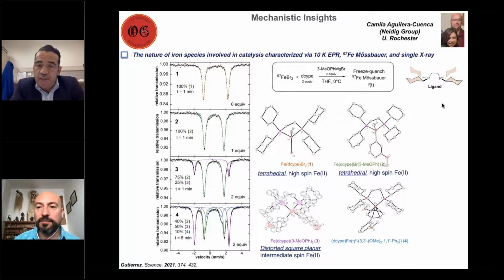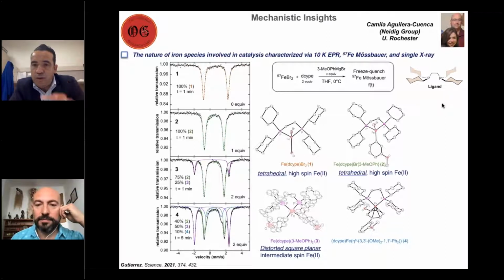Yeah, you can identify that. You can assign them, but I would argue that you really need extensive, and I mean extensive, collaborations with experimentalists, because any DFT method in reality could predict anything to be lower in energy. So if you just focus on, let's say, species number 1, like shown here, the tetrahedral high spin, and if you use different functionals or different basis sets or different multi-reference methods, they're all going to predict different species being the lowest energy, whether that's the low spin, medium spin, or high spin.